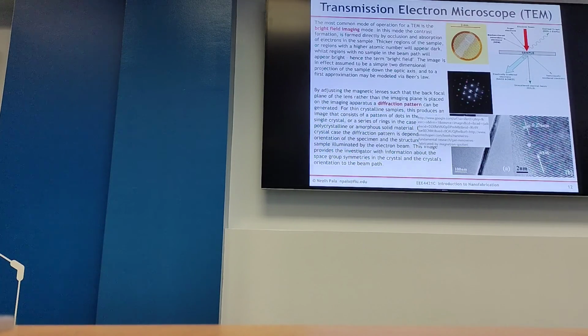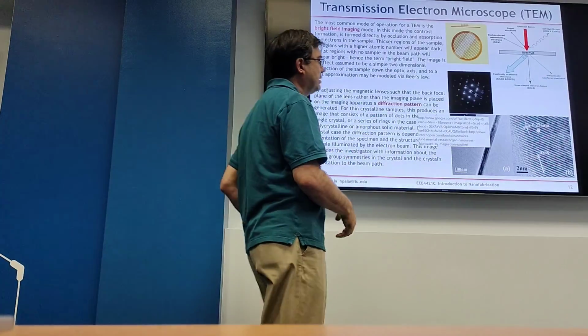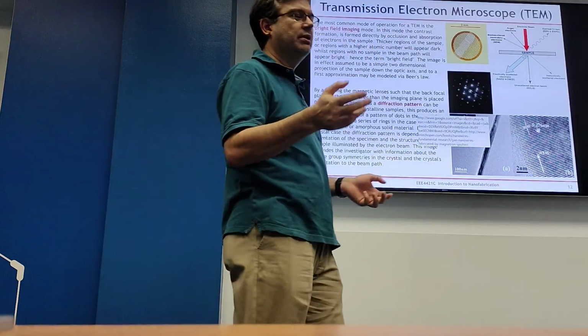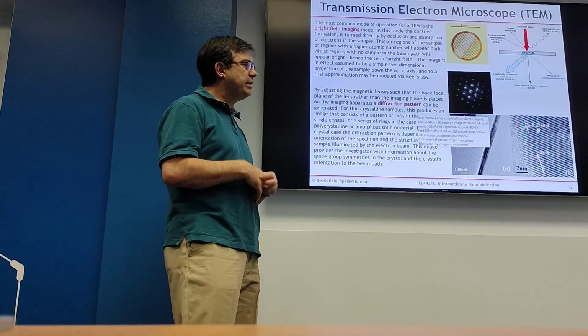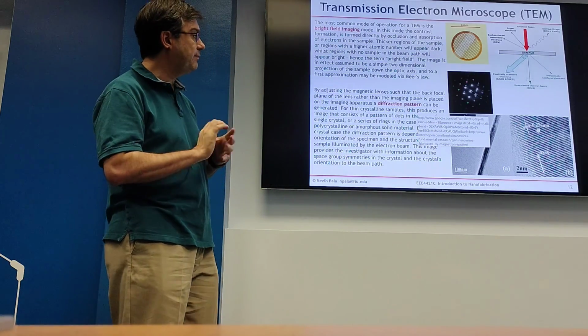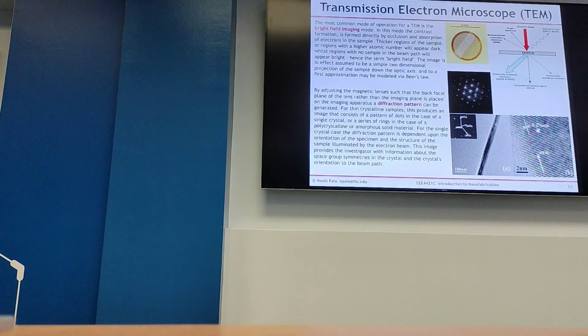See, those are individual atomic layers, okay? And the distance, as you see here, is 2 angstrom, 0.2 nanometer. It's extremely small, so it's also called HR, high resolution TEM. It allows you to see if your sample is a good crystal. If you have something like that, it shows very good crystallinity. Especially if you work with nanomaterials like carbon nanotubes, nanowires, you can see if they are single crystalline, or what the structure looks like. So very, very convenient. This is based on the intensity of transmitted electrons.